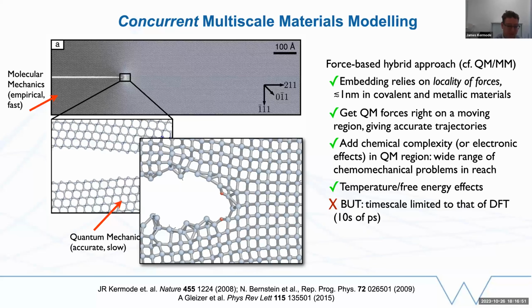And we can look at that by treating this small region again here with an accurate method like density functional theory, embedding it in a very large system like this. And we can describe as much chemical complexity as we like, providing it's localized and providing it can be described adequately with our quantum method of choice. This is a dynamical simulation, so we get temperature and free energy effects included automatically.